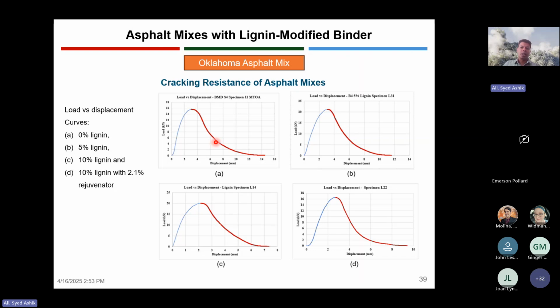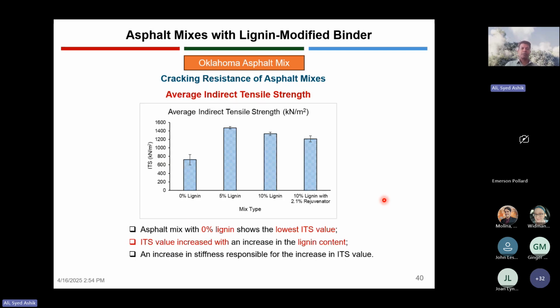Also, if you closely look at the post-peak slope, which indicates whether the material is ductile or brittle, we have seen that the slope became more and more steep. As a result, we can expect a more brittle behavior of asphalt mixes with the addition of a higher amount of lignin. And here are the results for the indirect tensile strength that we have calculated from the same test, the IDEAL-CT testing.